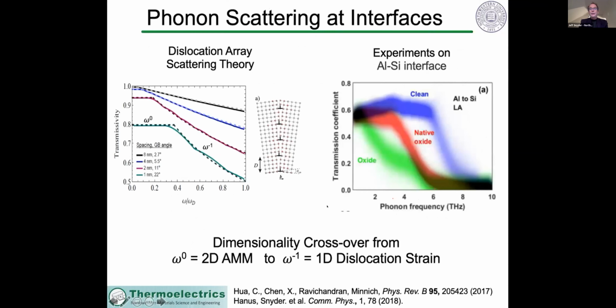So in our group, for example, we think that there's a dimensionality crossover such that at very low frequencies, you get an interface type scattering from a two-dimensional surface that is frequency independent, like we expected before. But at higher frequency, there's a dimensionality crossover that reflects the nature of the interface in a grain boundary, for example. So in materials science, we know that low angle grain boundaries in particular can be described by periodic arrays of dislocations. And the dislocations are one-dimensional defects, not a two-dimensional interface.